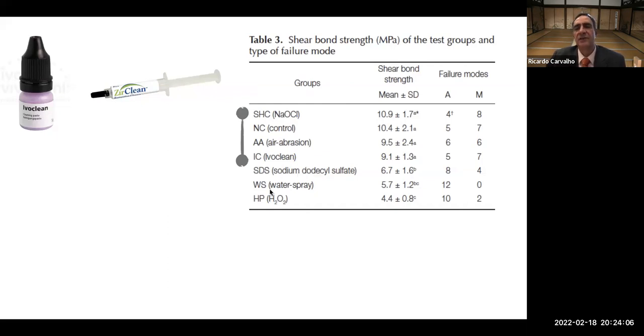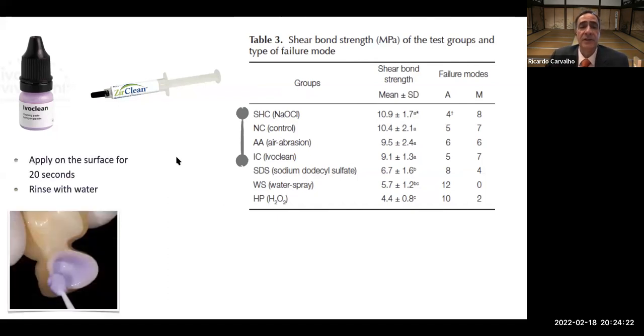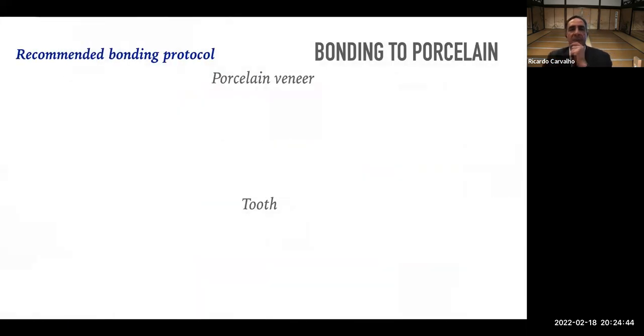Detergents are not so effective, just water is not so effective. Hydrogen peroxide is not effective at all, so do not use. Actually, I ended up compromising because of excess oxygen in here. So my recommendation is that you go for some of these commercial products that might be available there. So after you try in, there is contamination, you can apply these on the surface for 20 seconds and rinse with water. It's a pretty straightforward, very simple procedure that we apply, and we clean the surface for cementation.